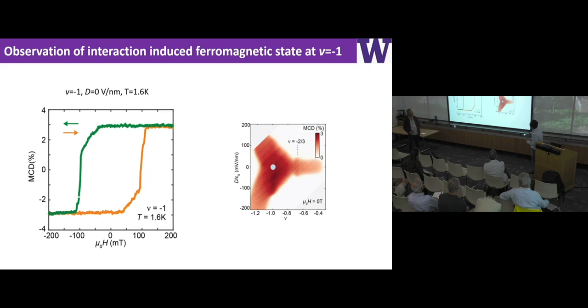The reason is that when you apply an electric field, you redistribute the electrons between the two layers. The calculation shows that at a certain displacement field, the electron wave functions from the top and bottom layers overlap the most, and we need this overlap for the direct Coulomb exchange that gives rise to these ferromagnetic states. But if the electric field goes even larger, you push all the electrons into one layer, and the ferromagnetism vanishes because the system becomes layer polarized.